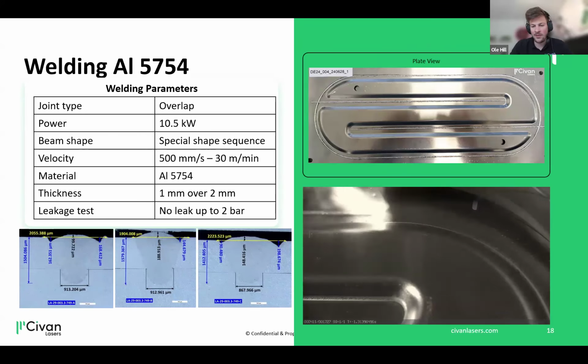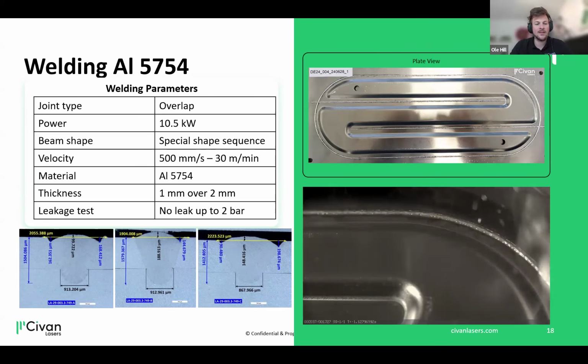Going to a kind of related topic is an example of an aluminum plate cooler. In this case, it is aluminum 5754 series, and this is a cooler that we designed ourselves just as an example of what you can do. So we don't have it under any NDA because we ourselves ordered these plates. Here we can reach real high speeds, like 30 meters per minute. It's like 3 times faster than what I showed you before. And this is an overlap configuration of 1 millimeter over 2 millimeter. We found that to be quite the common application in aluminum cooling plates.